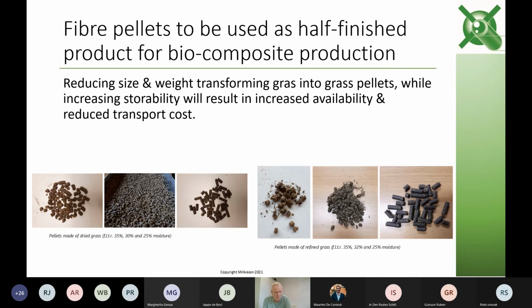The nice thing of making these kinds of pellets is that it depends on the process conditions that you are making these pellets. That's also depicted in the images. There is one image missing, and that's at even lower moisture content. What you can see, if you still have too much moisture present in your grass fiber, you're not getting nice compact fibers, but it's more fibrous-like. Whereas on the other side, if you go to even lower moisture content, roughly 10%, your pellet is no longer a pellet, but it will transform into powder, which you don't like either.